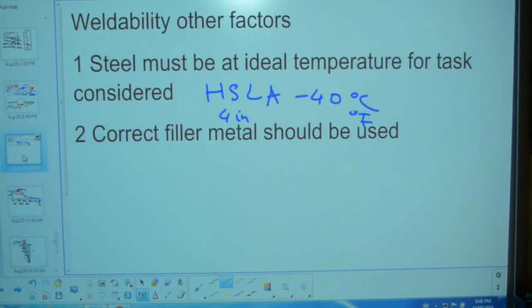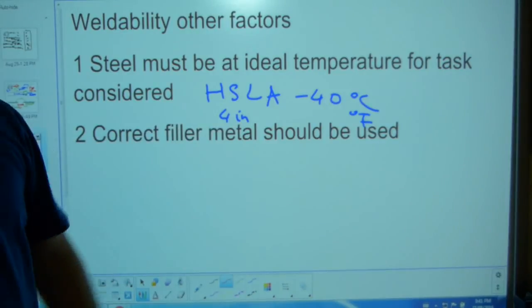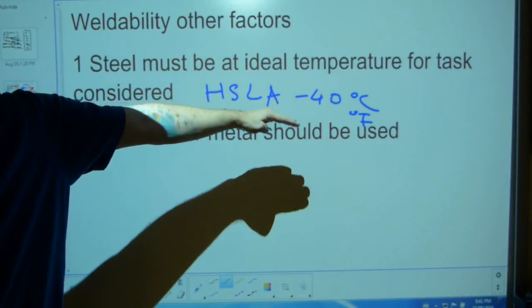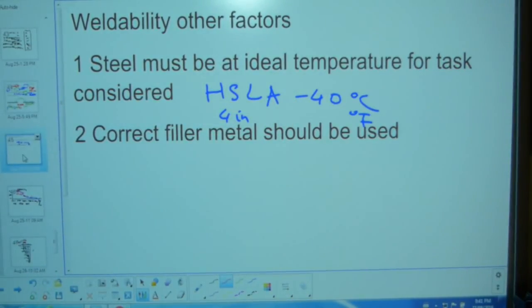Last remarks here: the Alaskan pipeline story is not so much weldability, but a little bit of welding technique mixed into it. Steel must be at the ideal temperature for the task considered. Some of the high strength low alloy steels were developed for cold service environments such as the Alaska pipeline, at negative 40 degrees Celsius or negative 40 degrees Fahrenheit, because it doesn't matter which scale it is. That number happens to be the same spot on both of those scales. So if you're welding pipe and the pipe goes through a thermal shock when the heat of the welding process hits it, it's going to be cracking everywhere, and that's not good.